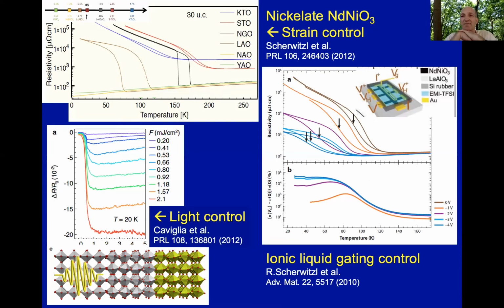basically all of them. So here what you see is data for resistivity versus temperature of neodymium nickel O3, one member of this family that has an insulating to metallic to magnetic insulator transition. And you see how you can actually switch or move around the transition temperature and also change the amplitude of its hysteresis by changing the substrate. So this is NdNiO3 grown in rather thick form on a number of different substrates.